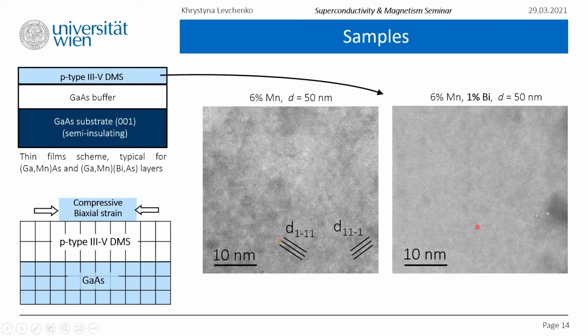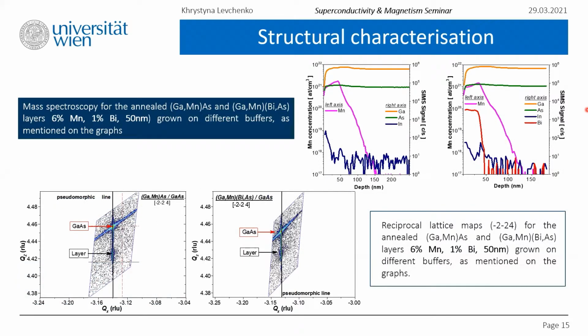The only thing under question is this cloudy contrast here on the right-hand side, and it originates from uneven thickness of the thin film, as no defects like mosaicity or dislocations are visible in the vicinity. Looking at the 10 nanometer scale, we may see that both ternary and quaternary compounds, of two distinct color hues, show perfect zinc-blende structure with absence of defects. But images taken at various sample spots and in various scales in general show high-quality structures with minor defects. High quality of the films was also confirmed by other techniques, namely high-resolution X-ray diffractometry and secondary ion mass spectroscopy. So let us start with the first one.